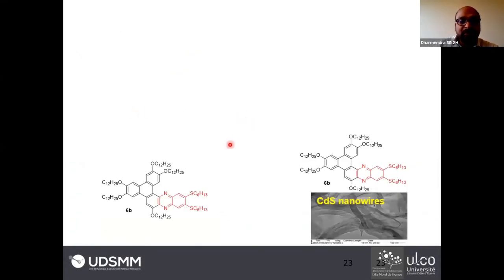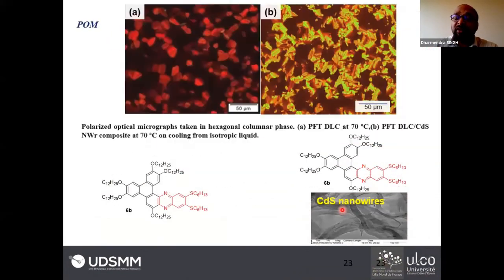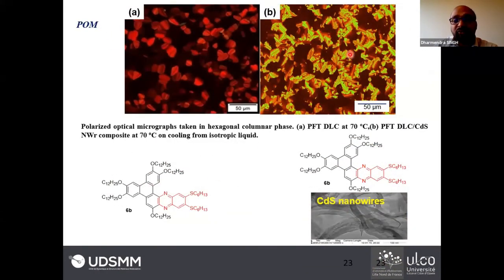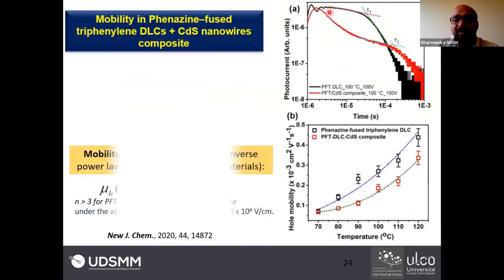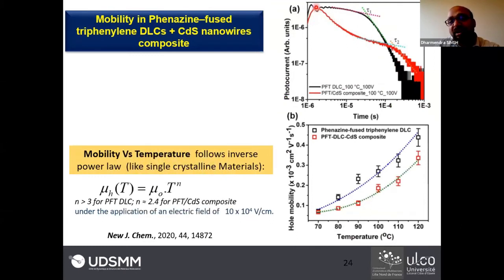Later on, we also investigated the triphenylene system doped with the CDS nanowires just to check whether this nature persists or not. And you see here, by adding the CDS nanowires at a very small concentration, the molecular ordering changes. So we again recorded some time-of-flight measurements, and by the insertion of this CDS nanowire, the nature of the transient curve changes. The value of mobility is slightly decreased, but it keeps the same nature as a function of temperature. So this hole mobility is a function of mu naught times T to the power n, where n can be changed in the pristine system and in the doped system.